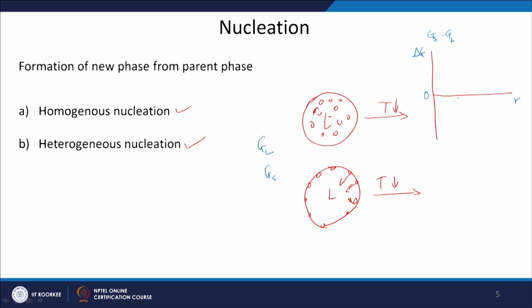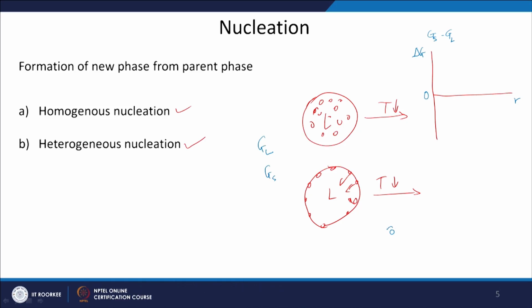But the problem is that when you want to have a new phase coming, you will have a new interface between solid and liquid. Some change is there because the stable phase is now solid, so there is a decrease in free energy, but there will also be an increase in free energy because of the formation of the interface. So, what this does is it initially increases the free energy, and then the free energy decreases as the solid is growing. As a function of radius, I can have a small nuclei which is forming, and then it grows and becomes a bigger nuclei. So, I can draw a free energy diagram like this.